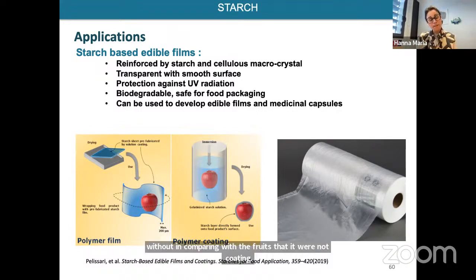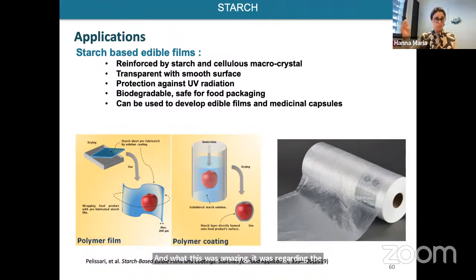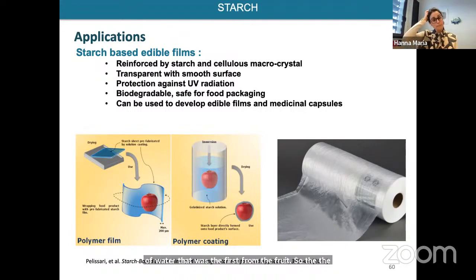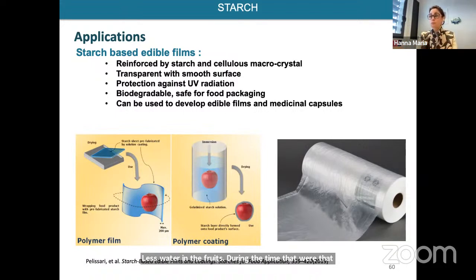Because we were looking for antimicrobial activity, but for sure starch doesn't have it. But even only with this coating, we see some progress compared with the fruits that were not coated. And what was amazing was the quantity of water that diffused from the fruit. So we lost less water in the fruits during the time when they were coated with the starch and starch nanocrystals, chitin nanocrystals.